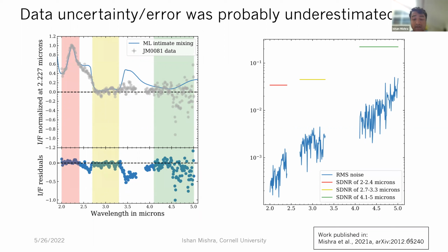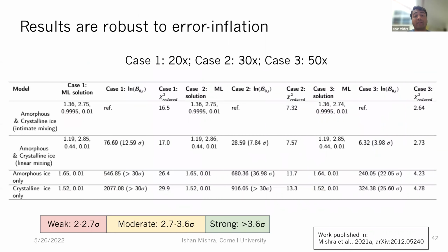The Juno data had a lot of calibration issues. For example, the data we are using is normalized to 1 at this wavelength because there were calibration issues. The noise was also not well characterized. So I took this as an indication that the noise is underestimated. We proceeded to inflate our error bars and see how that affects results, assuming our noise is underestimated, what would happen?